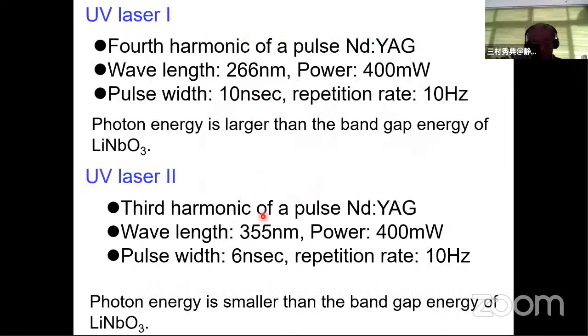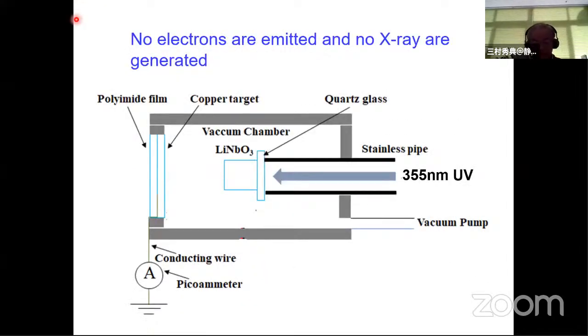When we used the 355 nanometer UV laser, the photon energy is smaller than the band gap energy of the lithium niobate. So in this case, the X-ray was not generated. When we irradiated 355 nanometer UV light directly onto the lithium niobate crystal through the quartz glass, no electrons were emitted and no X-ray was generated.